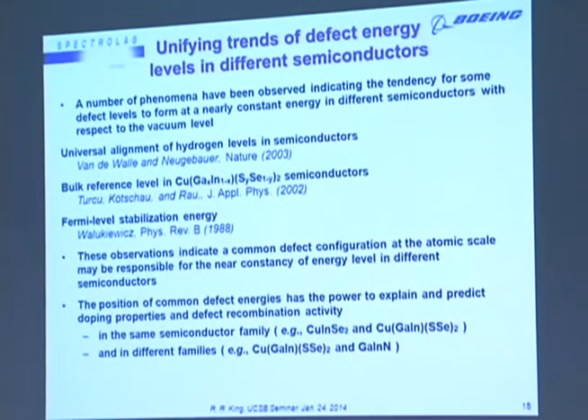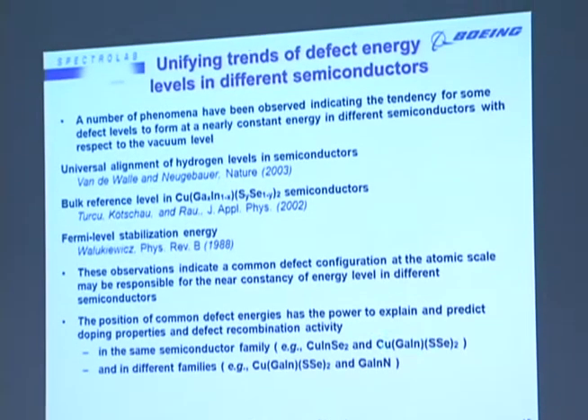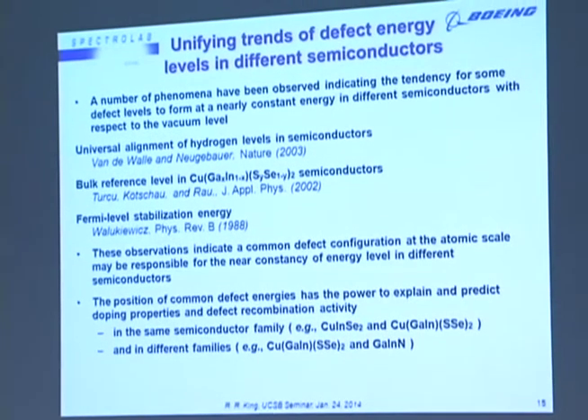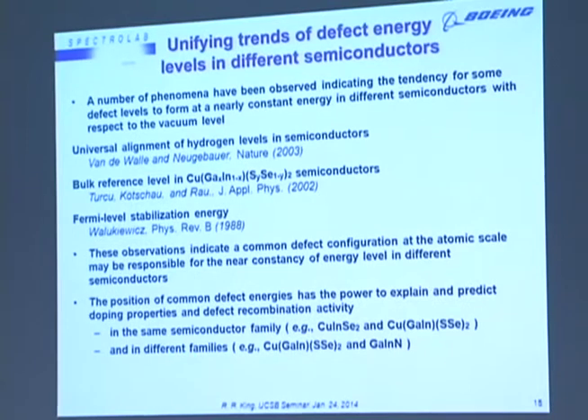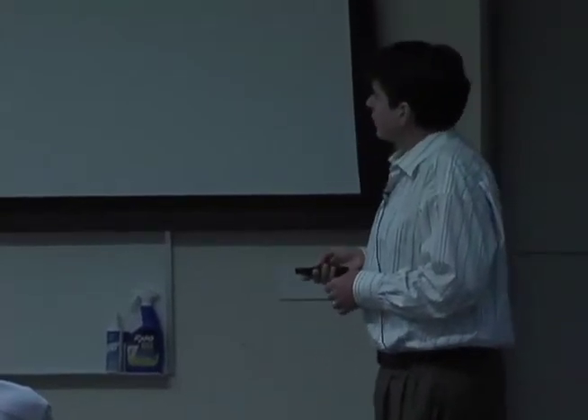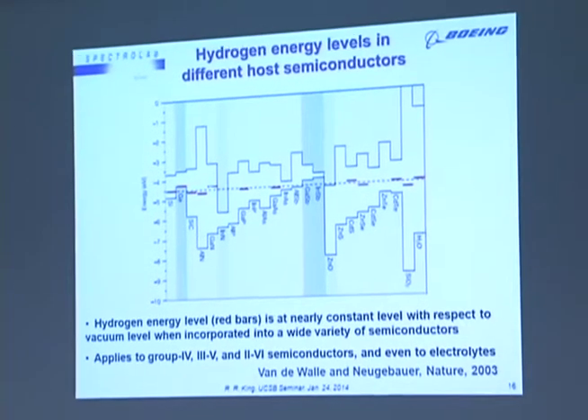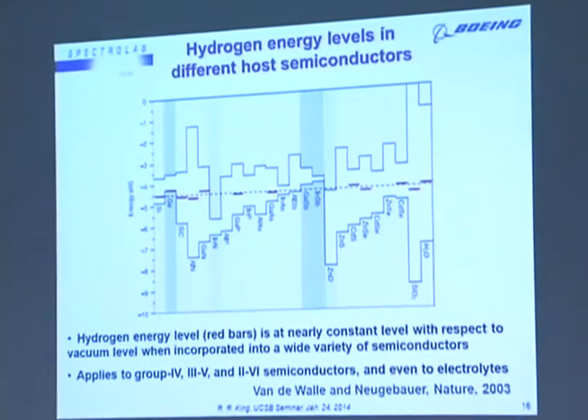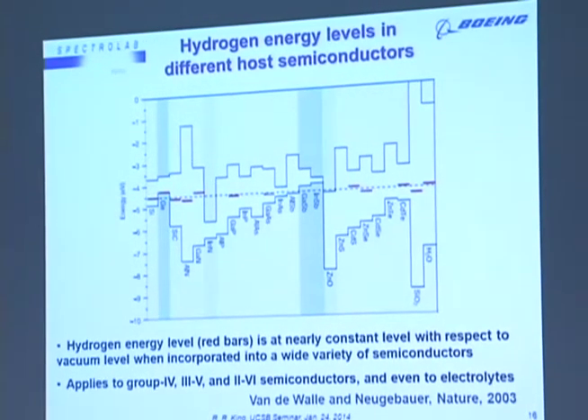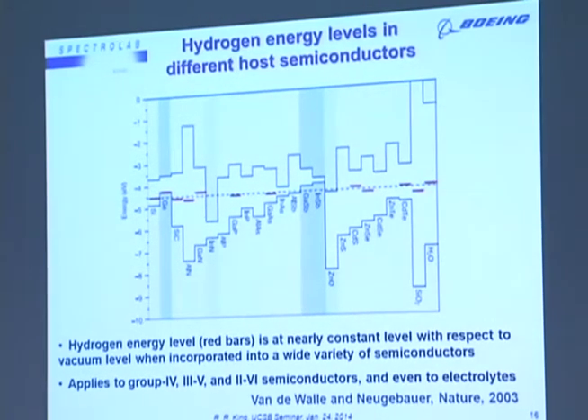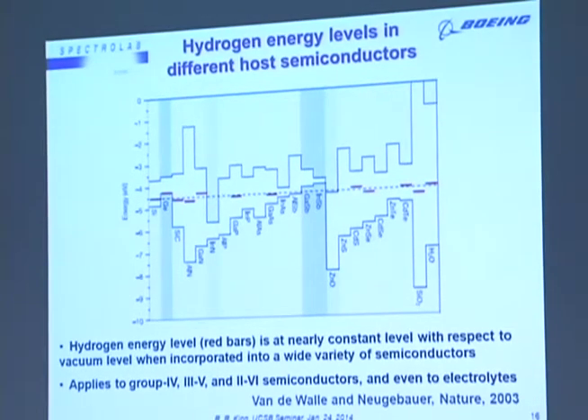For instance, considering wider bandgap chalcopyrite materials compared to the parent material of copper indium diselenide, and even looking at different families. So some aspects of copper indium diselenide may even apply to gallium indium nitride, both being polar covalent, covalently bonded semiconductors. So the theoretical work done by Van de Walle shows these constant hydrogen energy levels for a whole host of these semiconductor materials. So you can see that all of these are lining up very convincingly and somewhat surprisingly a constant difference in energy from the vacuum energy.